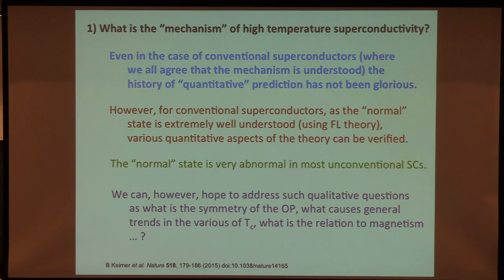For instance, in the iron-based superconductors, you have multiple Fermi surfaces. You have, say, an electron pocket and a couple of hole pockets, and the sign changes as you go from the electron pocket to the hole pocket, but it's still S-wave. It's the sign change that's the sine qua non of a mechanism from repulsions. That doesn't mean D. It doesn't mean D. In fact, you can get triplet superconductivity out of this sort of mechanism. You can get S-wave. You can get F-wave. It depends on details of the Fermi surface and on the details of the interaction, but in ways that actually aren't that hard to work out.